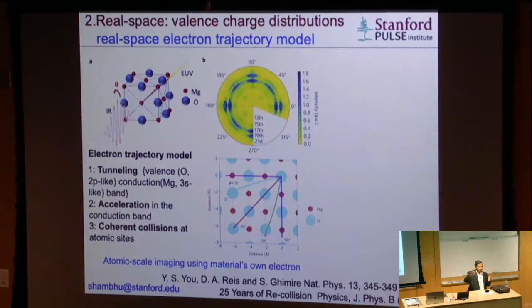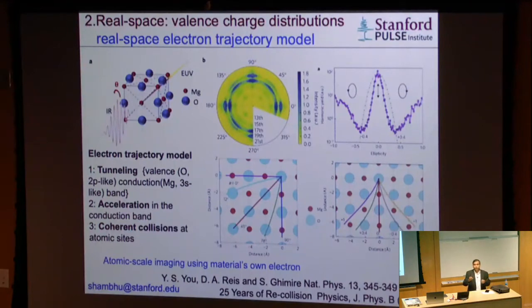Kind of similar to the nitrogen molecule experiment, right? So here you can see the strong emissions along certain directions, and essentially nothing in some other directions for a linearly polarized laser field. And the nice thing about the laser is, you can play with the polarization of the laser itself, right? So our student did. He changed the laser from linear to elliptical and to fully circular, and basically watched how harmonic intensity changes as a function of polarization. And that's the raw data. Then he got out of the lab and he had to think about what the heck is going on in there, because of these maxima and minima and so on, right?